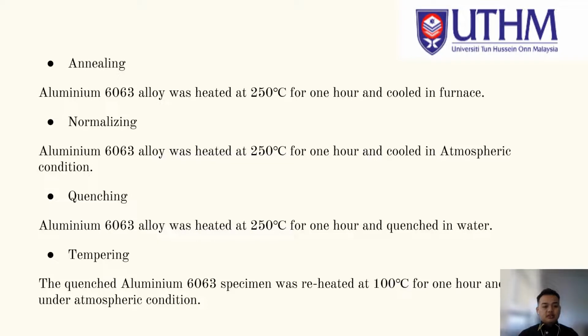The second is normalizing, the process of heating the metals near its recrystallization temperature and cooling at room temperature. In this paper, aluminium 6063 alloy was heated at 250 degrees Celsius for 1 hour and cooled in atmospheric condition. Third is quenching. Quenching is the process of heating the metals near its recrystallization temperature and cooling rapidly using quenchant. In this paper, aluminium 6063 alloy was heated at 250 degrees Celsius for 1 hour and quenched in water.